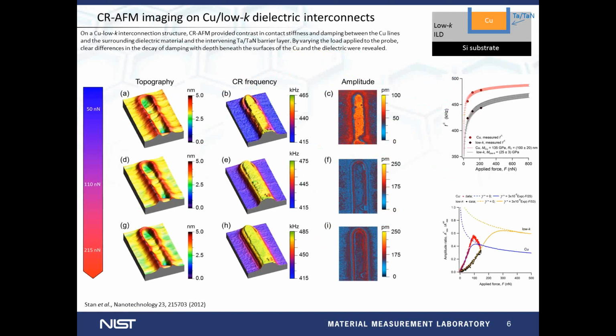Now, once we understand and control the dynamics and contact geometry of CR-AFM, we can look at different materials and structures. Here is an example of mapping copper low-K dielectric interconnects. The structure is shown schematically here, with copper lines separated from low-K dielectric by a thin tantalum nitride diffusion barrier. We have topography, contact resonance frequency, and amplitude maps made at different applied loads. The topography remains unchanged as the load varies, but we have substantial differences in both contact resonance frequency and amplitude between these three materials at each applied force.